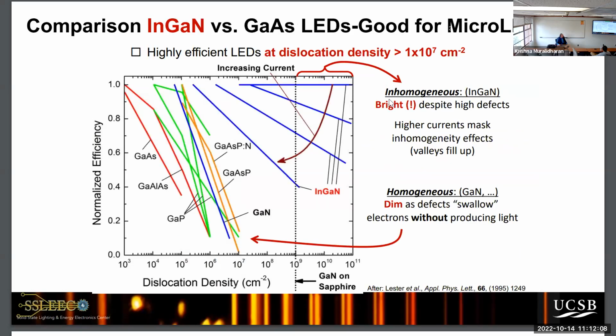So what we did was we introduced indium into the crystal, and that helped solve a lot of this efficiency drop because, so a normalized efficiency of 1 also means 100%. So it turns out if you add indium to gallium nitride, and here's gallium nitride. So what happened is as you increase the number of defects, up to about 1 million defects per square centimeter, the efficiency would drop from 100 down to less than 10%. So it turned out if we added indium, which we needed to do anyways to get the color, suddenly the crystal became bright. And this is actually one of the things that Dr. Nakamura got the Nobel Prize for.